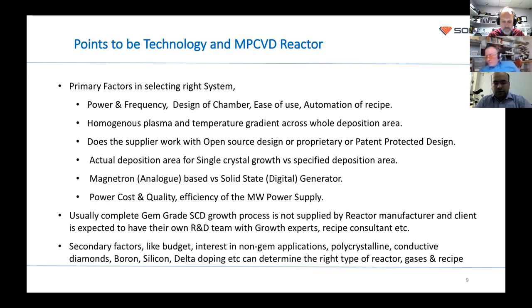You also have a choice in selecting your magnetron — either analog or solid state. Power cost, power quality, and microwave power supply efficiency are also important. Reactor suppliers typically don't provide the process recipe — they expect the client to set up their own R&D team to develop it. Other factors include your budget and application: whether you want to grow single crystal, polycrystal, conductive, boron-doped, or silicon-doped diamonds — all determining the type of reactor, gases, and recipe you'll need.